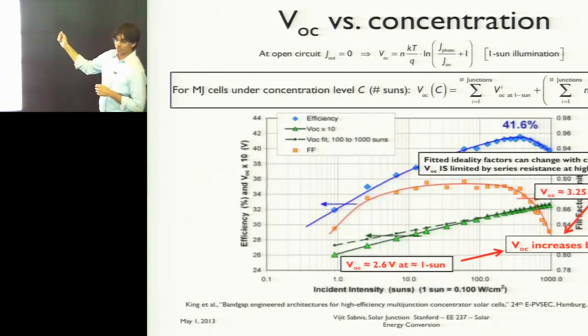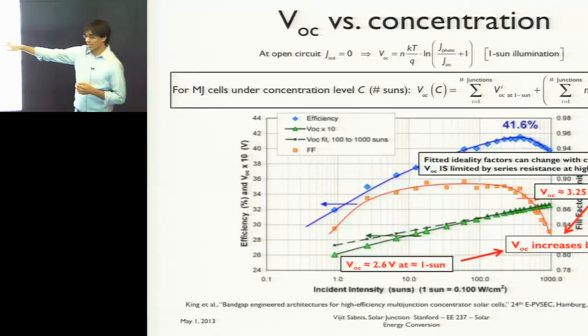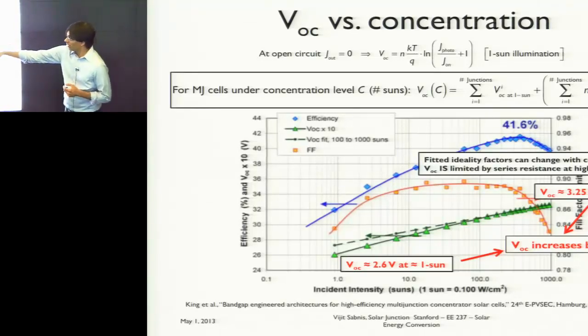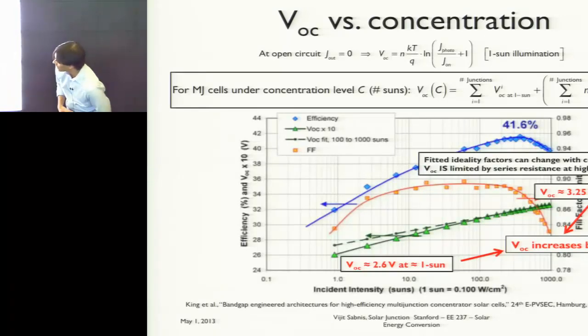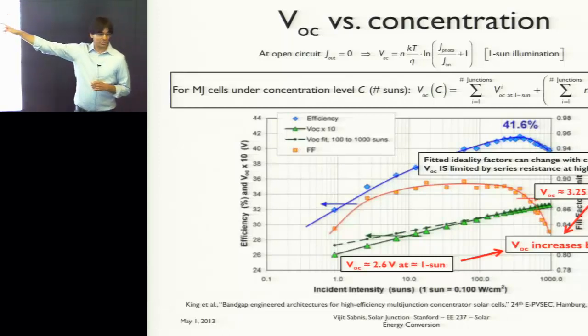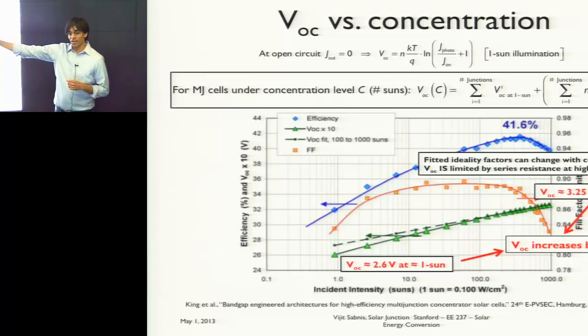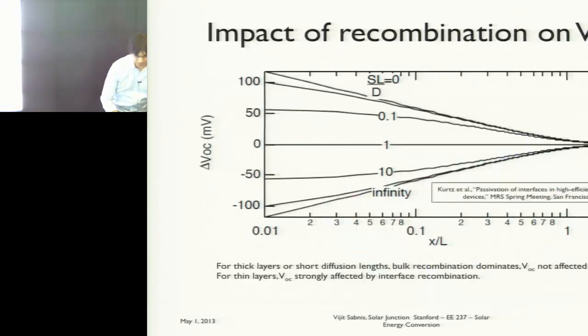Your current goes up linearly. And that's why at 1 sun, the efficiency of these solar cells is relatively low. In this case, it looks like it's 26%. Do I get that right? No. At 1 sun, it's about in the low 30s, and under concentration, it's over 40%. Now, what you'll notice here is if you look at efficiency versus concentration, that efficiency increases, so it tracks your VOC, but eventually that efficiency rolls off. And that's because of series resistance losses within your solar cell. And I'll talk about that here in a moment.